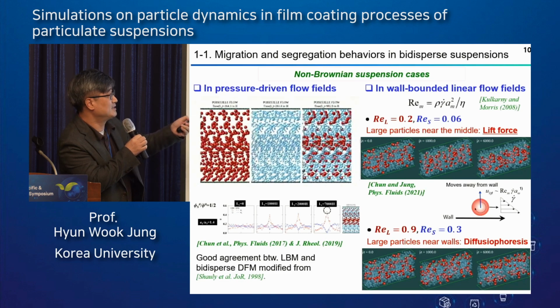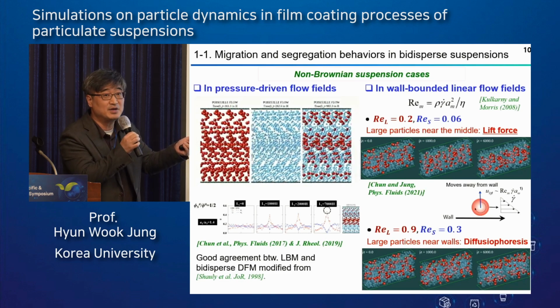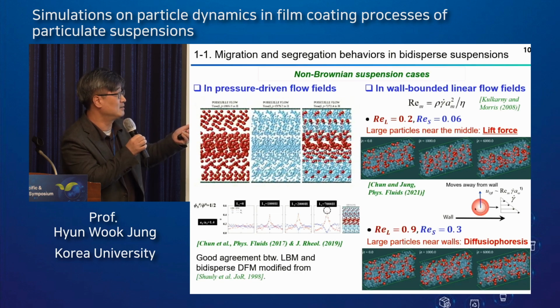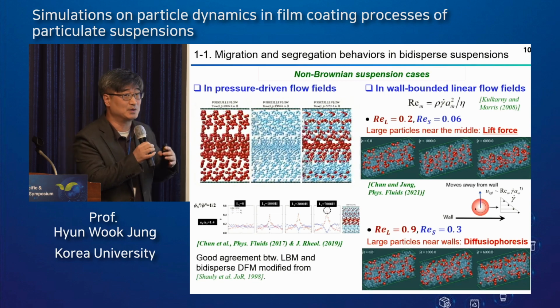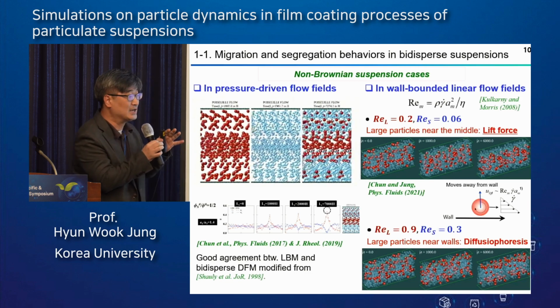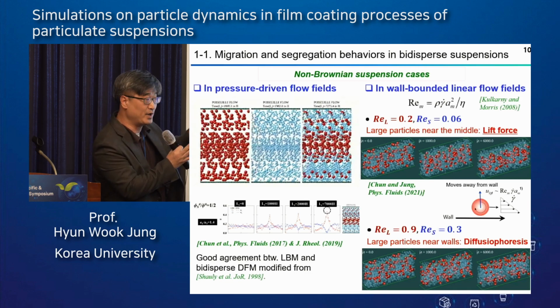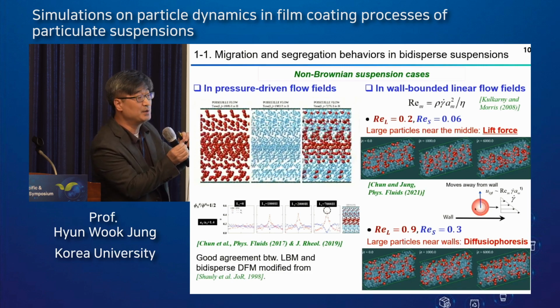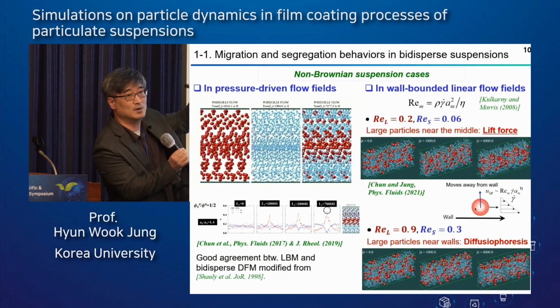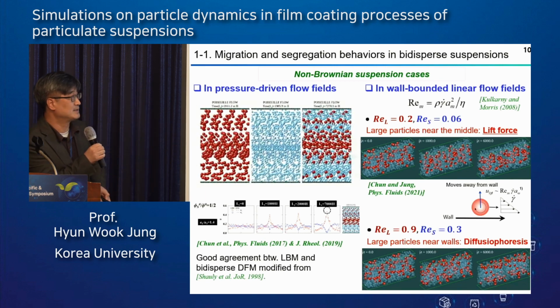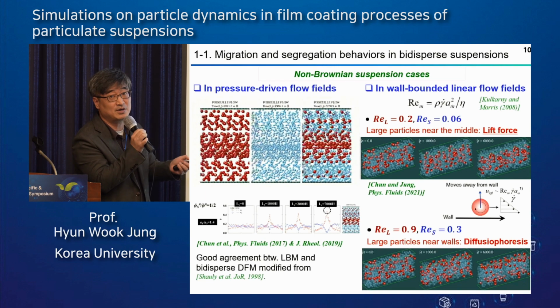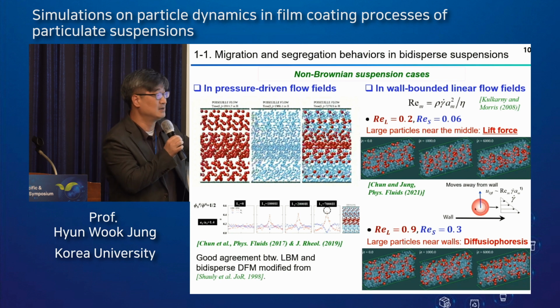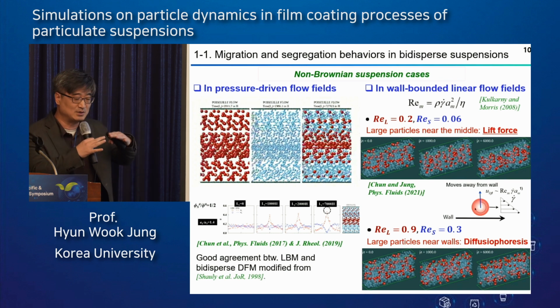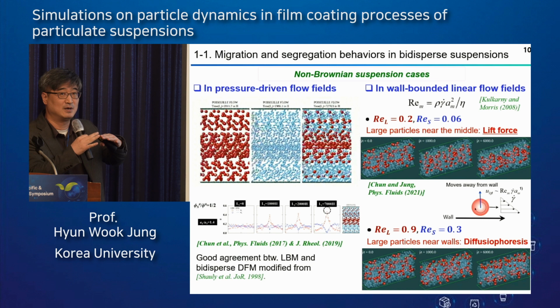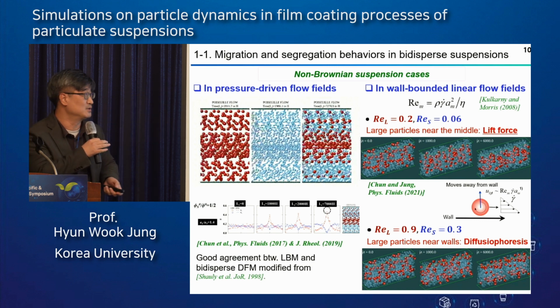In the bidispersed case, finally, we can see some segregation behavior between the large particles and the small particles, due to the different shear-induced diffusivity. So large particles first move toward the mid-plane, and the small particles will be depleted from the mid-plane, moving toward the wall, as shown here. Clear segregation behavior. Also, we found this segregation behavior using a modified continuum-based model, the diffusion flux model. So there is good agreement between the transient response of segregation behavior from the LBM and the diffusion flux model.